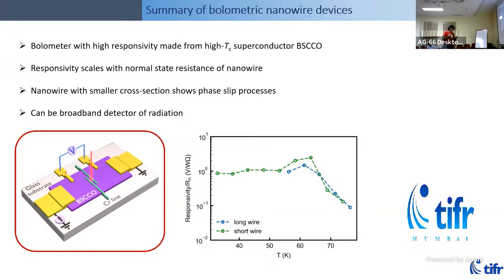This platform of using high temperature superconductor allows you to make these bolometric detectors which work at or very close to liquid nitrogen temperatures, and one can engineer the responsivity. Right now, one of the drawbacks is that either the geometry or the contacts have to be optimized. The noise equivalent power is somewhat not optimized, and that's something that we want to try. Particularly, hooking up these circuits so that we can launch RF into them and look at detection using RF response is something that we are immediately thinking of doing.